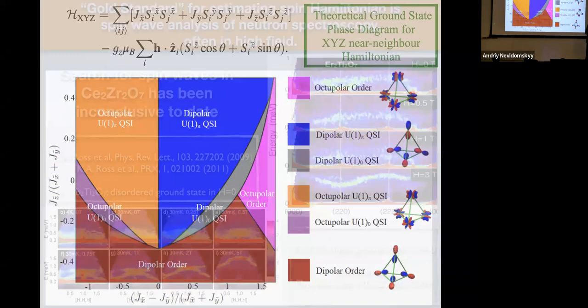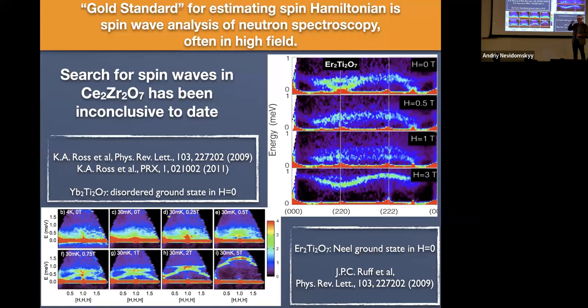And if we were dealing with a system that only had magnetic dipole moments, then this would be, well, it wouldn't be easy, but we know how to do it. The gold standard for estimating spin Hamiltonians for magnetic dipoles is to measure the spin waves in the system and then fit the spin waves to spin wave theory or some more sophisticated version of spin wave theory and back out the exchange Hamiltonian. And so we've kind of made a career out of doing this sort of thing. So here's some early work on a different pyrochlore and another different pyrochlore. And if you don't have sharp spin waves in zero field, you can apply a field and get sharp spin waves.